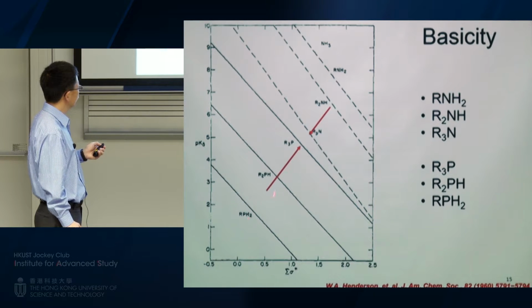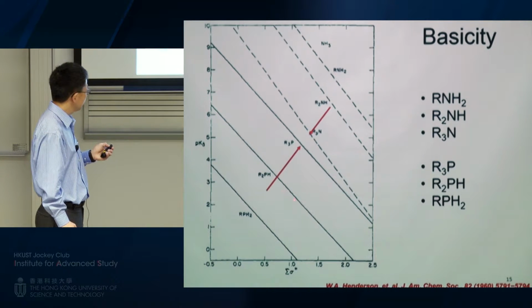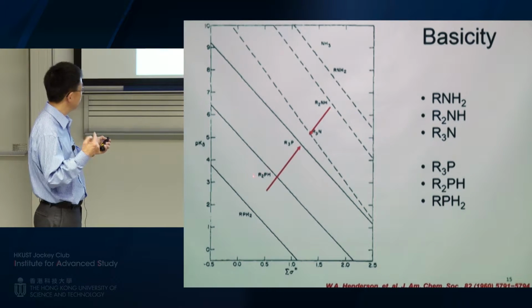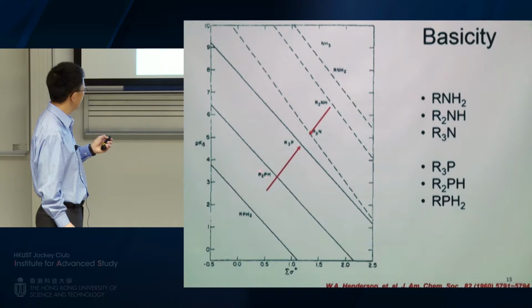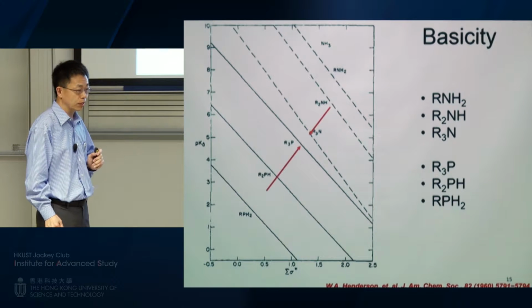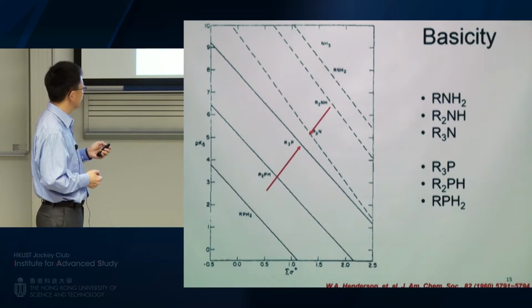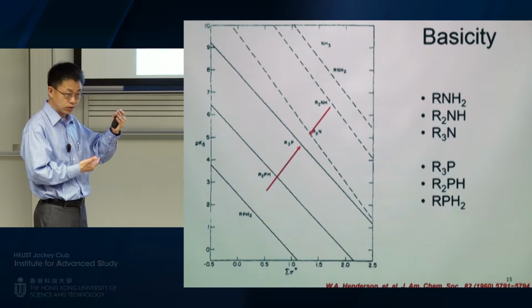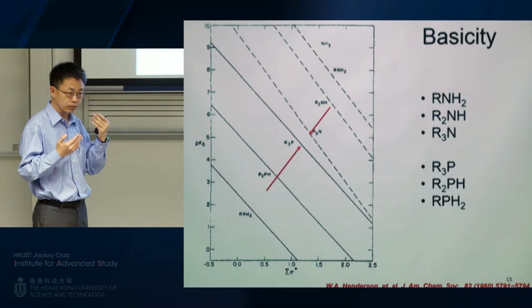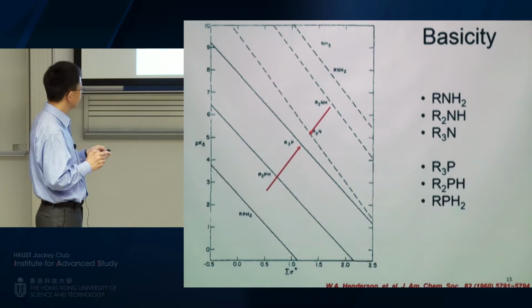But if you look at phosphonium or phosphine, very interesting. You have this primary phosphine, 1R, and then secondary phosphine, meaning two hydrogen atoms get replaced by an organic alkyl group, and tertiary phosphine, the basicity is actually going up. So this is the direction you want to go. So our imagination was, if you allow the quaternization, they may actually switch. You might have a basicity out of the phosphonium higher than ammonium. So that was very, very exciting to us.